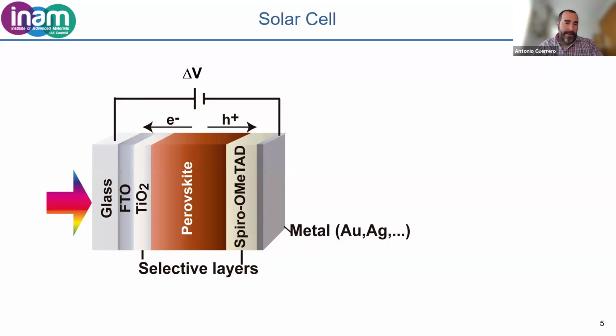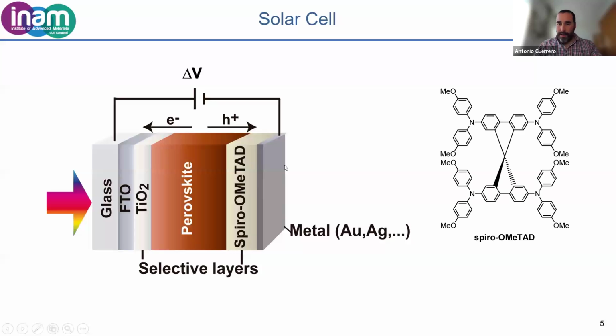But the device works thanks to the fact that we can illuminate it through the transparent electrode. The light will come to the active material, in this case the perovskite. We will photogenerate electrons and holes, and we need to separate them, which is quite easy to do in perovskite. But these electrons and holes need to be collected in the selective layers. In this case, electrons will be collected by the TiO2, and the holes, the positive charge, will be collected by the spiro and the metal on the top. Okay, so this is just to show you how spiro looks like. This is an organic molecule, but as I said, several materials have been used in the literature.